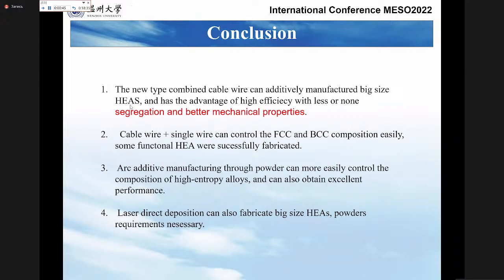Third, arc additive manufacturing through powder can more easily control the composition of high entropy alloys, because we can change the powder composition. For the wire it's harder, because we mix the wire and twist it together. Fourth, laser direct deposition can also fabricate big size HEAs. Powder requirements are necessary because it has special requirements for the powder size, the powder shape, and so on.